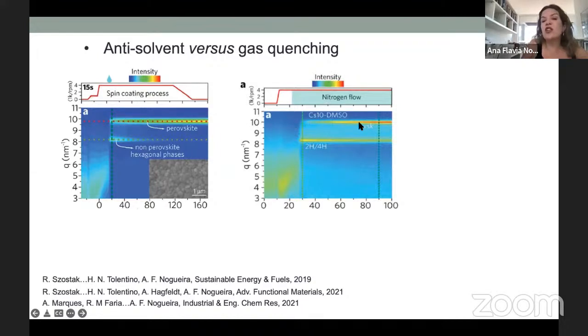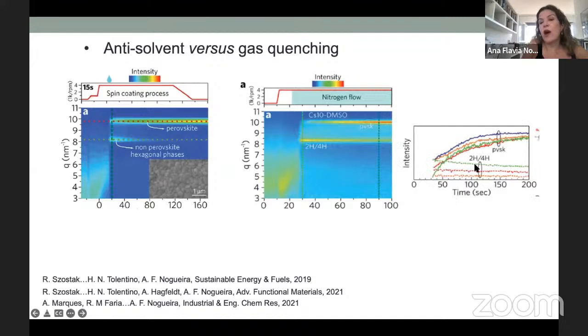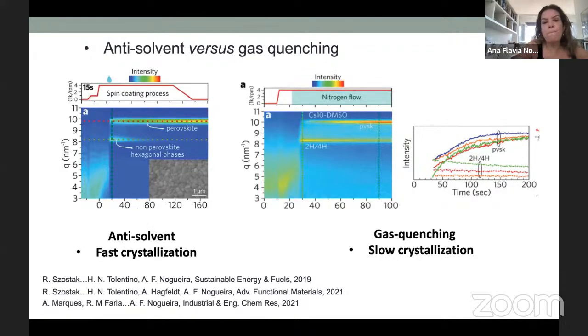So the crystallization is much slower when you use this method, but you still have the formation of the hexagonal phase. Even at the end of the experiment, you still have the formation of the hexagonal phases. So again, first you form the hexagonal phases, then you form the perovskite. So that means that here, after this deposition, the annealing step is really, really important to remove all the hexagonal phases prior to assembling your device, okay?